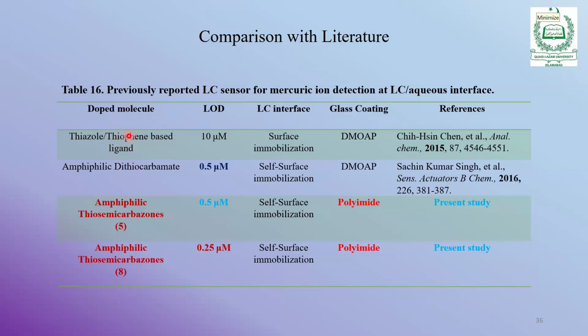different doping molecules have been used as ligands, with different liquid crystal interfaces and glass coatings. Here you see a thiazole thiophene ligand was used. The LOD was 10 micromolar. With amphiphilic dithiocarbamate, the LOD was 0.5 micromolar. And with our results, we see that the first one, polyimide, gave you 0.5 micromolar limit of detection, which is comparable to this one. And the thiazole one gave you even lower LOD, 0.25 micromolar. So these are good results. They are comparable, and in this case superior, to those reported in the literature.